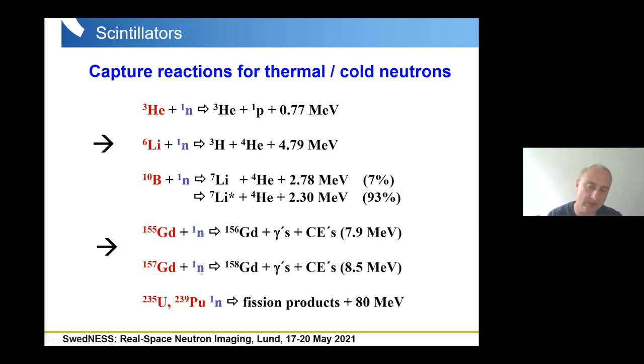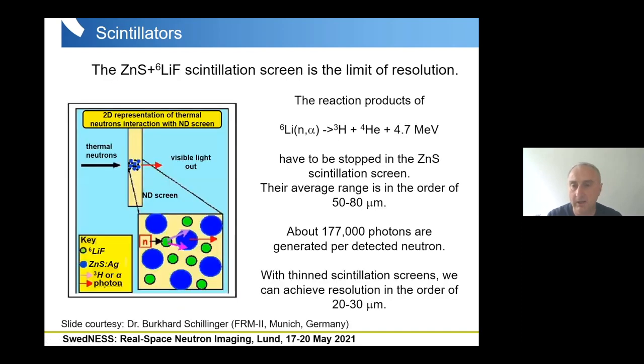The second reaction, or the second element, which we're using is gadolinium-based scintillators, where conversion electrons are produced. In this case, we have a not very big mean free path for the conversion electrons. And these types of scintillators are used for high resolution imaging. So you can see here the process of the detection of neutrons in the scintillating screen. This is a typical mixture of 6-lithium fluoride as absorber and zinc sulfide as the scintillating material.